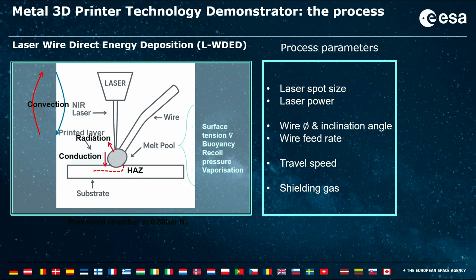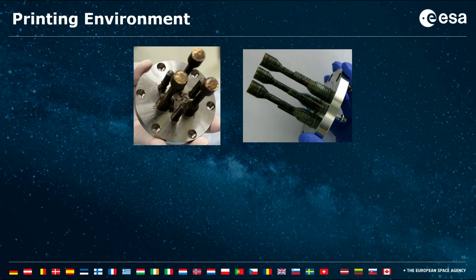And then you have a certain number of process parameters you need to play with to ensure that the quality of the part is good. It is the laser spot size, the laser power, the inclination of the wire as well affects the quality of the print, the speed, and the type of gas that you use. To monitor that, we had a set of sensors, basically consisting of a camera and a system to measure the height of the printed layer.